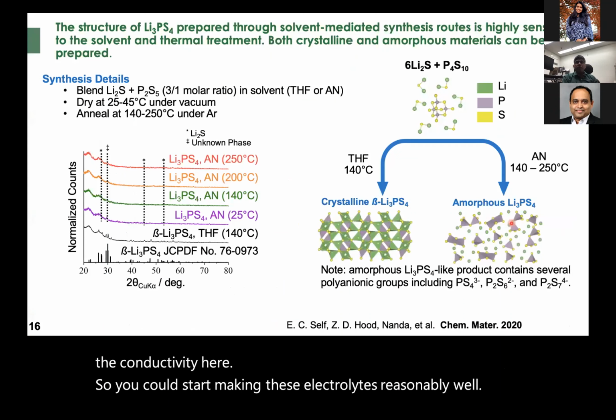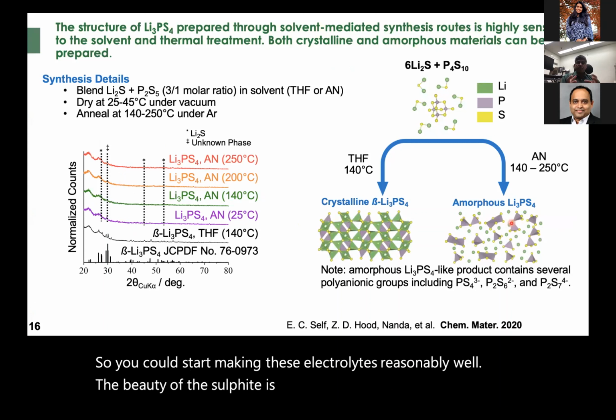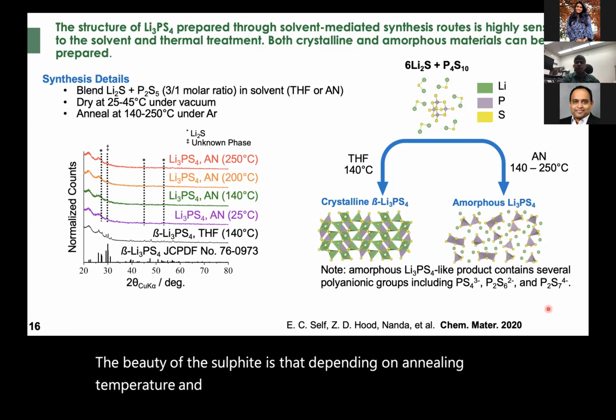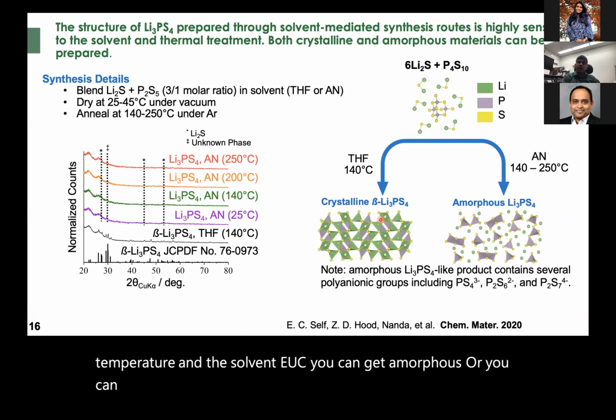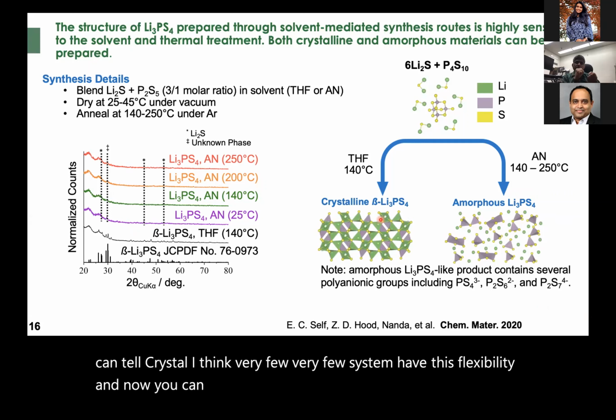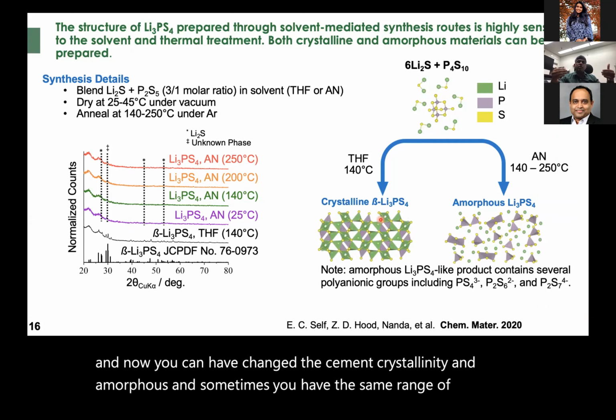The beauty of the sulfide is that depending on the annealing temperature and the solvent you use, you can get amorphous or you can get crystalline. I think very few systems have this flexibility, where you can change between semi-crystalline and amorphous, and sometimes you have the same range of conductivity. That's a very classic model.